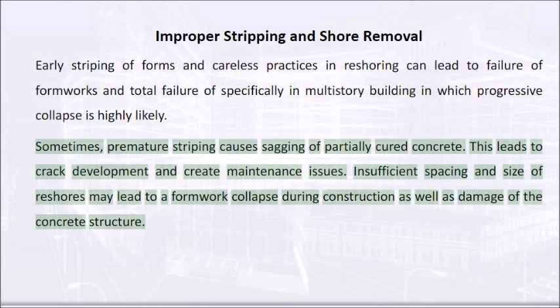Sometimes, premature stripping causes sagging of partially cured concrete. This leads to crack development and creates maintenance issues. Insufficient spacing and size of reshores may lead to a formwork collapse during construction as well as damage of the concrete structure.